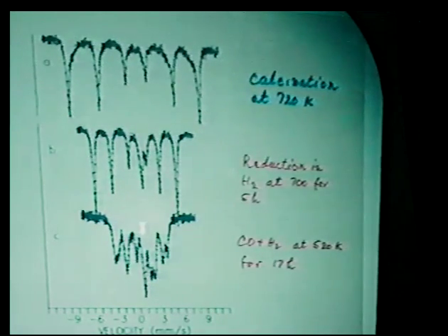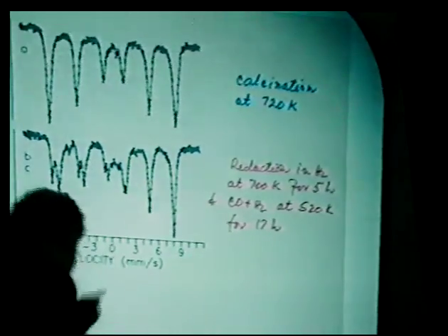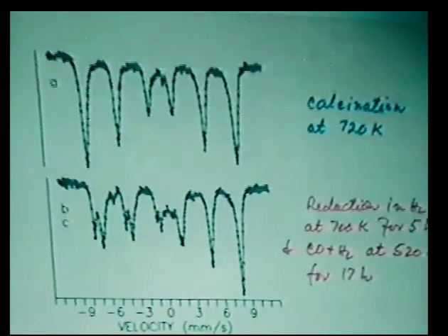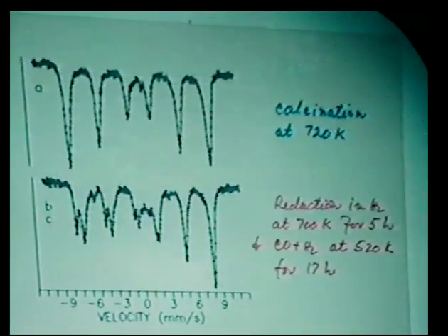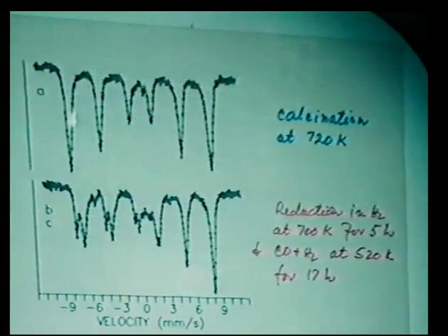So in fact, large particles are immediately deactivated by formation of inactive carbide, and then the catalytic activity decreases. I do not have catalytic activity data for this sample here. On the other hand, by having 10% iron on magnesia plus 1 to 8% alumina in here, the calcination results in the same spectra as before without alumina,